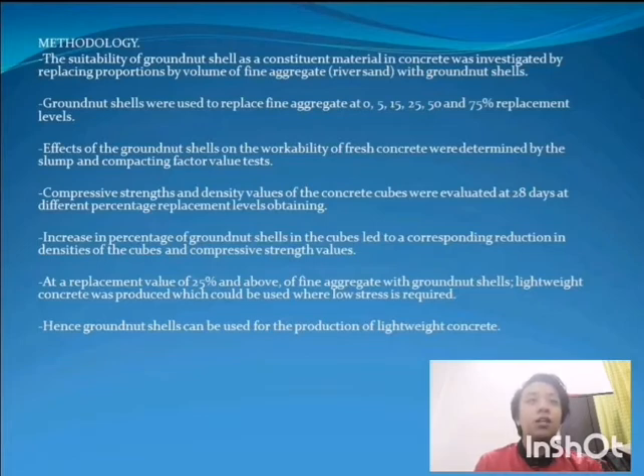The effect of the groundnut shell on the workability of fresh concrete was determined by the slump and compacting factor value test. Compressive strength and density value of the concrete cube were evaluated at 28 days at different percentage replacement levels. An increase in percentage of groundnut shell in the cube led to a corresponding reduction in densities of the cube and compressive strength value. At the replacement value of 25% and above of fine aggregate with groundnut shell, lightweight concrete was produced, which could be used where low stress is required. Hence, groundnut shell can be used for production of lightweight concrete.